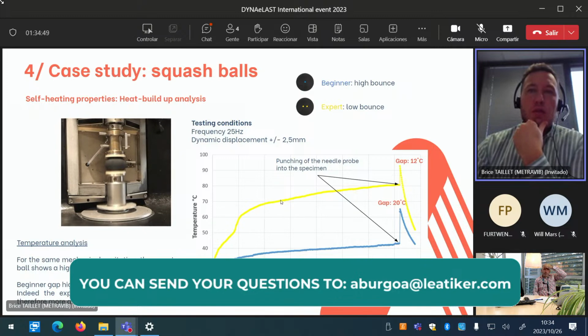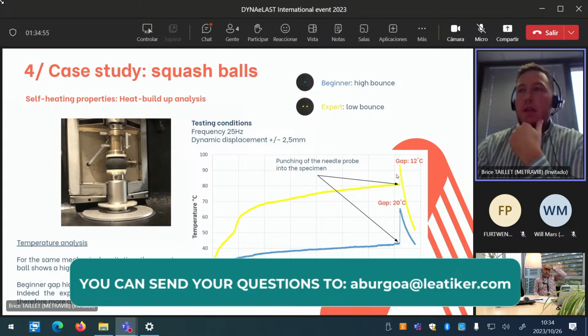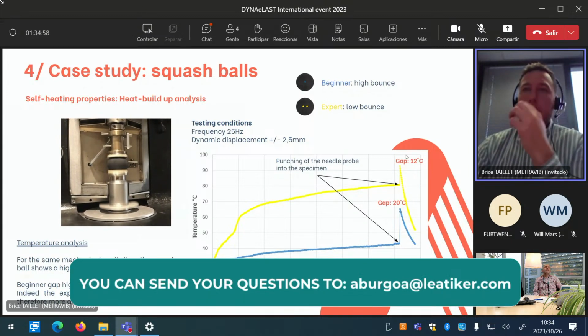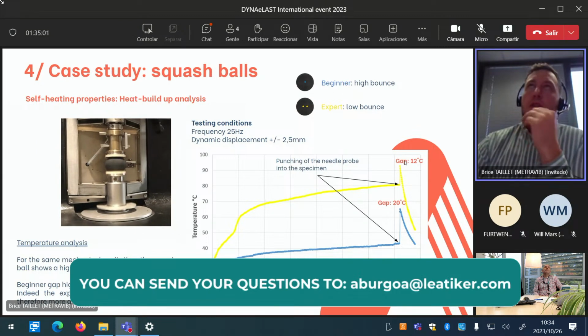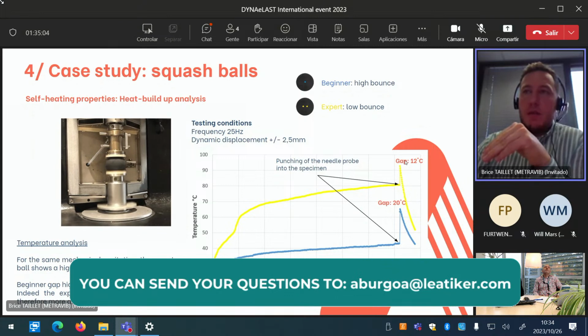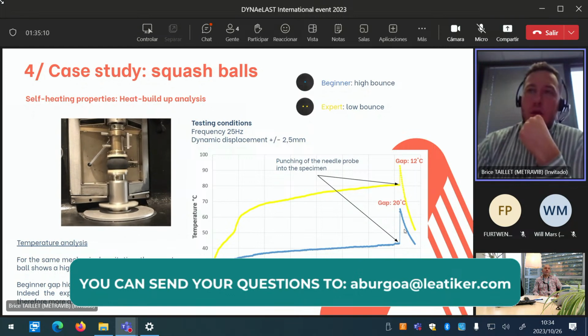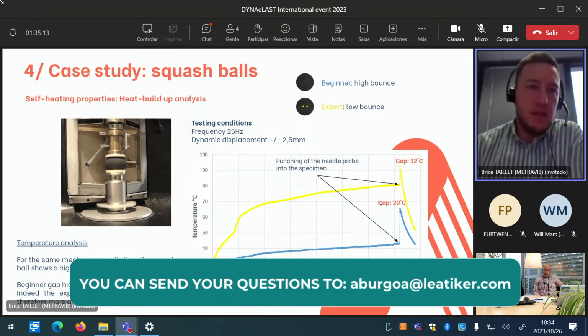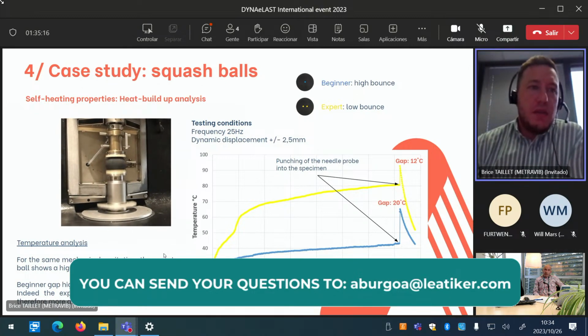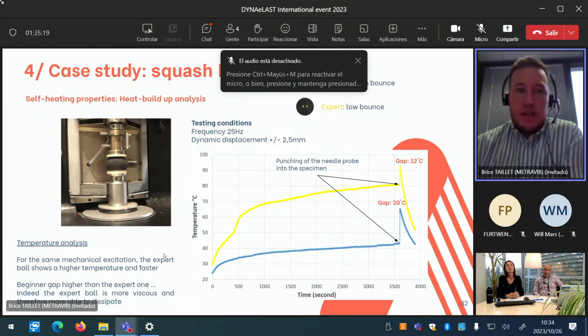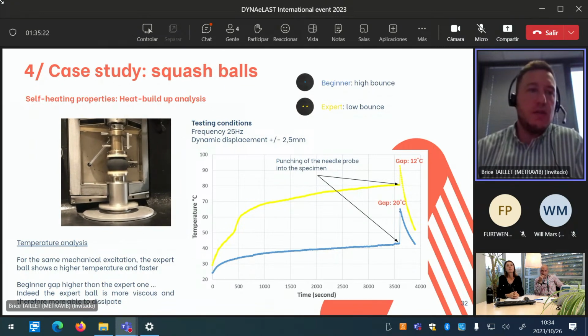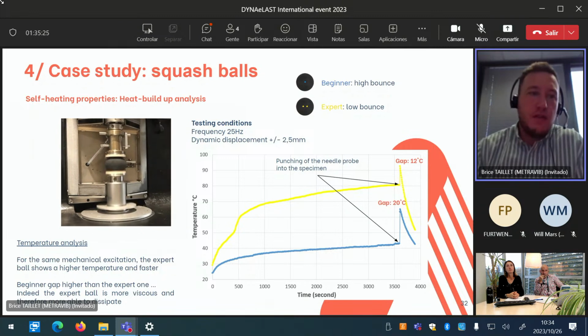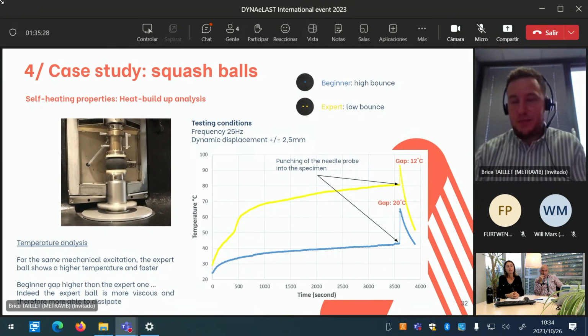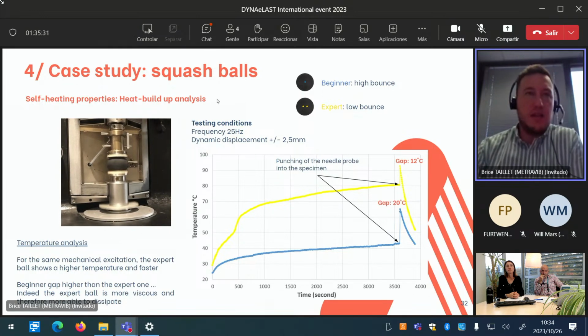The evolution of the temperature at the surface, and at the end of the test, we inject the needle to get the internal temperature. The gap between the surface and the heart of the specimen for the yellow one was 12 degrees. The gap is much higher for the beginner one because the gap is about 20 degrees. So once again, the beginner gap is higher than the expert one. This is totally logical because the expert ball is more viscous and therefore it's more able to dissipate. So we can easily show this aspect with this kind of test.